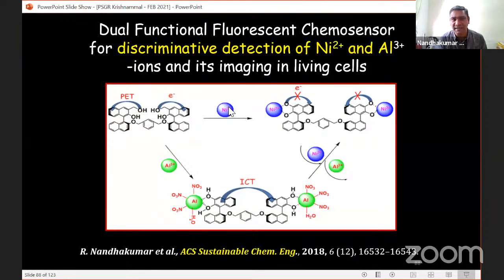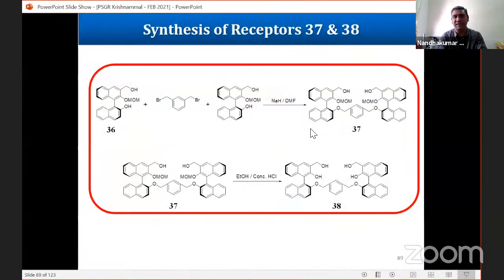It can sense nickel as well as aluminum. Here, this is the binol-based molecule sensor. It is meant for chiral recognition purposes, but it even detects metal ions. Through the internal charge transfer process, it detects aluminum. First it detects aluminum, and then if you add nickel, the aluminum is displaced and it detects nickel. So nickel is bound more strongly to the receptor than aluminum. So it is a dual type receptor, and the synthesis is shown here.